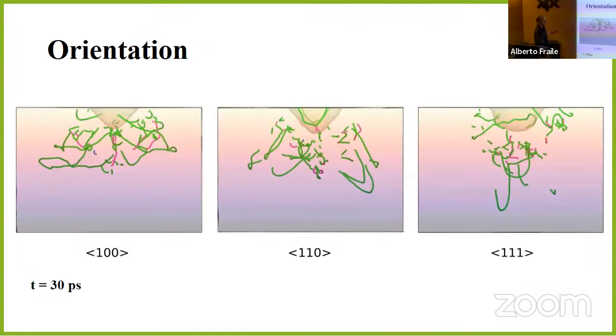And much more. We can also analyze the differences between different orientations. The target, I didn't say it, I think, but the target in all the results that I presented is this 100 orientation parallel to the impact. So in this case, we have this kind of dislocation forest. For this orientation, in these cases, the velocity is the same and all that.